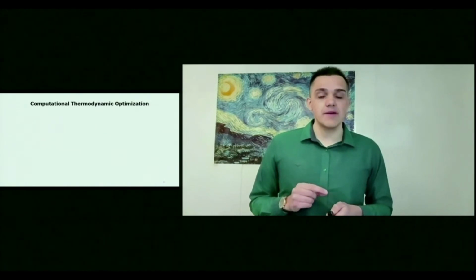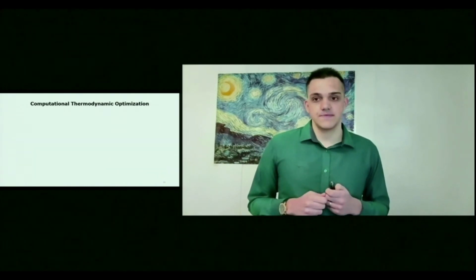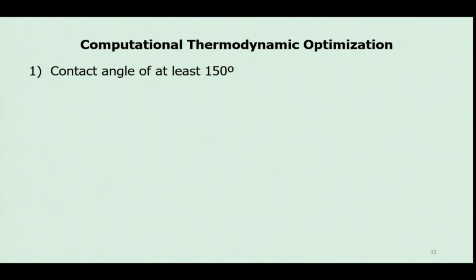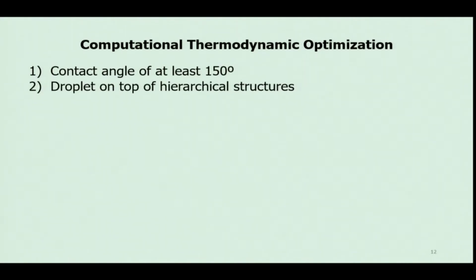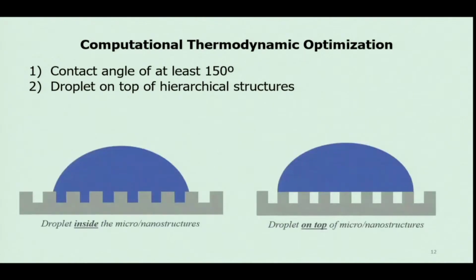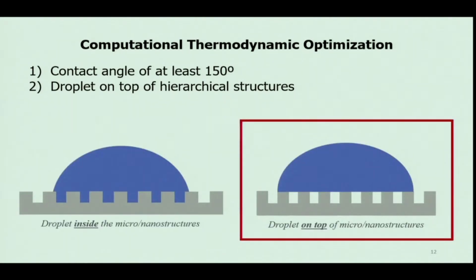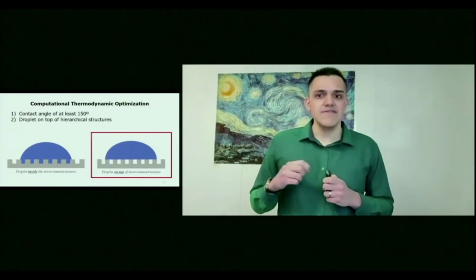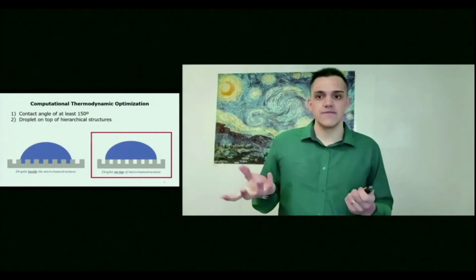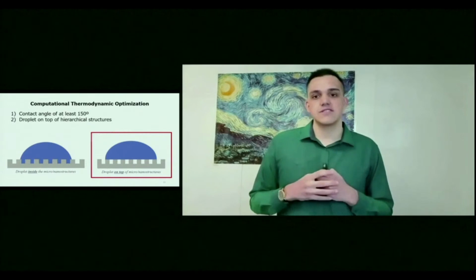The computational thermodynamic optimization considers 2 main factors. First, the final polymer must have a contact angle of at least 150 degrees. And second, the droplet of water should be maintained on top of the hierarchical structures, so that the water can roll off easily from the surface. In other words, we are decreasing the friction by reducing the contact area between the water droplets and the surface. Otherwise, if the water gets inside of the structures, like in the first image, even having a very high contact angle value, the water droplets will get stuck into the surface.